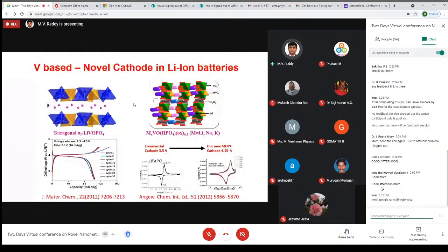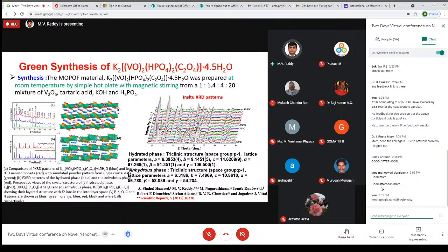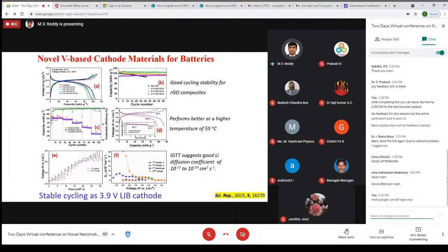I think people are looking for novel new materials. In fact, among them there are a few new materials that were reported for the first time in the literature. So these are vanadium-based novel metal-ion batteries, inorganic and organic. Compared to iron phosphate at 3.5 volts, we can see nearly 4.1. These materials have higher voltage, so we can get higher energy density. We looked into how to prepare them by green synthesis, prepared the samples and characterized them. Interestingly, we are able to get nearly 4 volts, or 4.1.